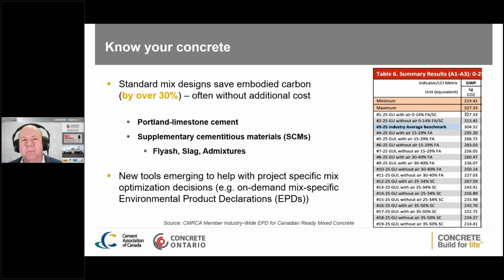So what's the worst? Not a big surprise when you use just GU cement and no supplementary cementing materials. So the first number that you see in that table, that gives you the highest carbon content. If we switch over to GUL, we immediately get an 8 to 10% reduction right off the bat. And then as we move through and start using different supplementary cementing materials, you get better and better impacts. So this was our first attempt to try and address or quantify what our carbon contents were across the industry.